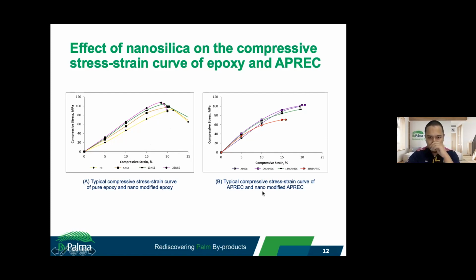While for APREC, as can be seen, all specimens which were incorporated with nanosilica had better resistance to compressive load compared to the pure APREC specimen during the 0 to 5% of compressive strain. And then after that, the curves of the specimens with 25% weight and 13% weight of nanosilica started to drop below the pure APREC specimen. The specimen with 5% weight maintained the highest slope gradient of the curve from the start until the failure.